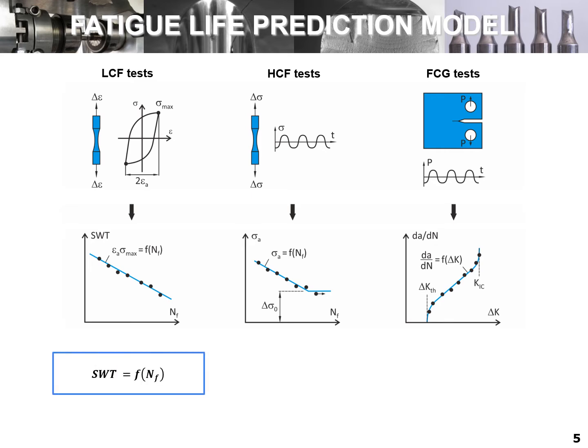Low cycle fatigue tests allow the definition of a fatigue damage law relating the SWT parameter with the number of cycles to failure. High cycle fatigue tests and fatigue crack growth tests enable the definition of the material characteristic size. Both the fatigue strength and the stress intensity factor range threshold are evaluated at the same stress ratio of the notched part.